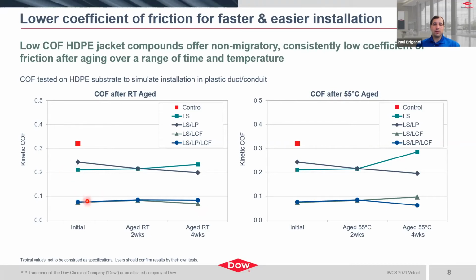So as we age the samples, you actually see stable coefficient of friction out to 4 weeks under the given aging conditions. So this is important because we're not utilizing typical migratory additives where you're looking for blooming to the surface, which can cause residue and loss of function over time. These are meant to be stable as we look at time and temperature.